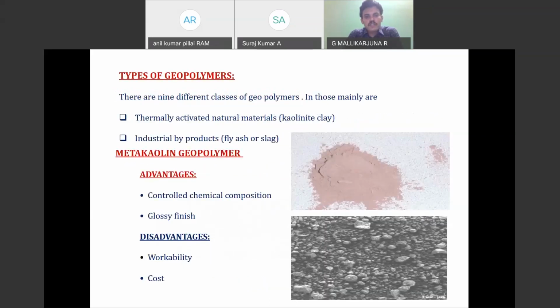Regarding the types of geopolymer, first there were thermally activated natural materials like kaolin clay, and industrial byproducts such as fly ash or slag. First they started with the activation of metakaolin. Metakaolin we also take as a source. One advantage is that we have a controlled chemical composition, and we get a glossy finish. The disadvantages are that it depends mainly upon the alkaline activator, we get less workability, and there is an increase in the cost.